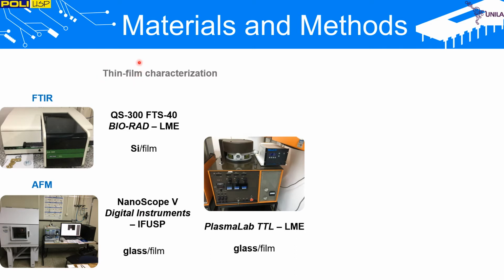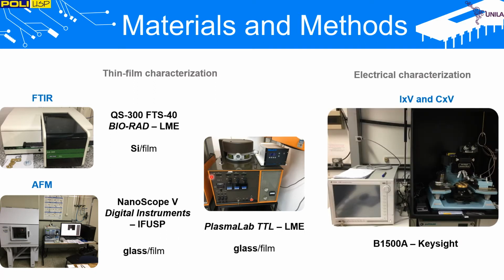Thin films of organic dielectric were studied by using Fourier transform infrared spectroscopy and atomic force microscopy. Also, the organic dielectric resistance was studied, analyzing the thickness variation as a function of O2 plasma etching. Electric devices such as capacitors had the current versus voltage and capacitance versus voltage curves extracted by a Keysight instrument in a micromanipulator.